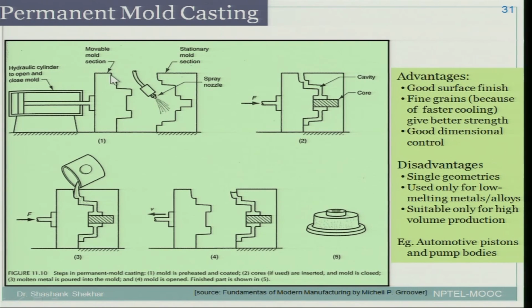In here we have something like this. This is the mold. These are the two pieces of the mold, as you can see, and when you put them together there will be a hollow region. This is the hollow region, and if you want to put a core, you can have a rod in over here, or even a sand core for that matter, and then pour the liquid metal. Now when you separate the two pieces of the die, you will have the required shape.